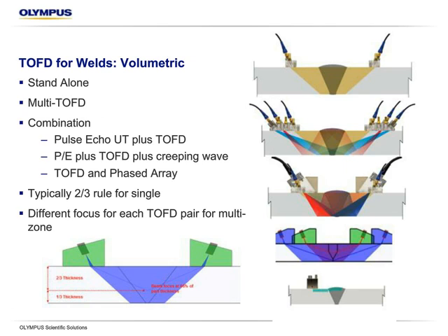So TOFD for welds, just a little bit more on the overview. It can be used as a standalone, just trying to do very quick screening or volumetric flaw detection of welds, typically using a single pair. A lot of times we use what we call the 2/3 rule. Without going too much into the complexity, we set the spacing of the PCS of the wedges so that the center beam that the wedge is designed for is basically intersecting the thickness at 2/3 of the nominal thickness. This will give us, usually with the proper frequency and size of probe, pretty much full volumetric coverage with small dead zones, and allow us to do a very good inspection.